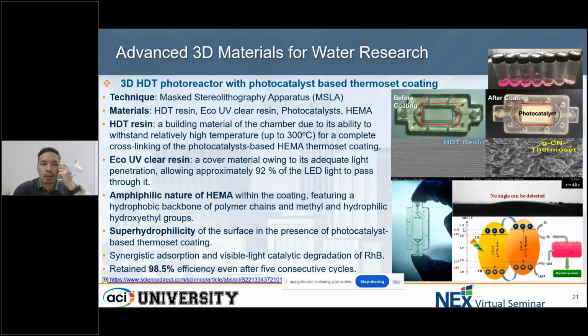Besides that, the photocatalyst that we coated is actually super hydrophilic, which gives very high water adhesion and a good surface area when we work on photocatalysis and also the adsorption process. We managed to retain 98.5% efficiency after 5 consecutive cycles, and even after 10 consecutive cycles, it still retains a high 90% efficiency.